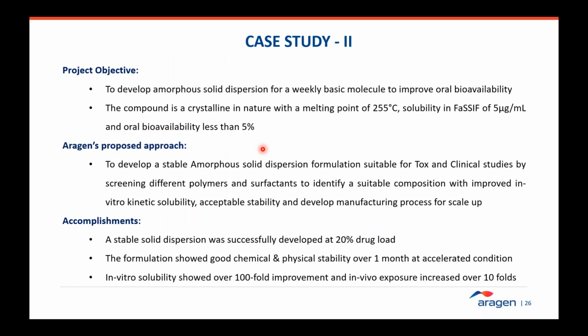So the second case study is very similar to the first one, but a different type of molecule. It's a weakly basic molecule with pH-dependent solubility. Though the solubility is quite good in low pH, at acidic pH, due to it's not a biorelevant media, not an absorption site for many compounds, it still shows very low bioavailability, just like a neutral compound where there's no solubility across the pH range. So this compound is also crystalline in nature with a melting point of 255 degrees and solubility in FASIF of about 5 microgram per ml with oral bioavailability less than 5%.